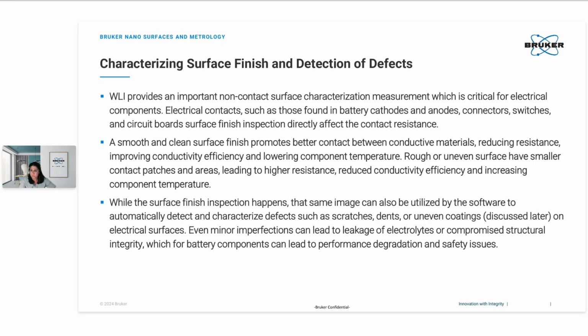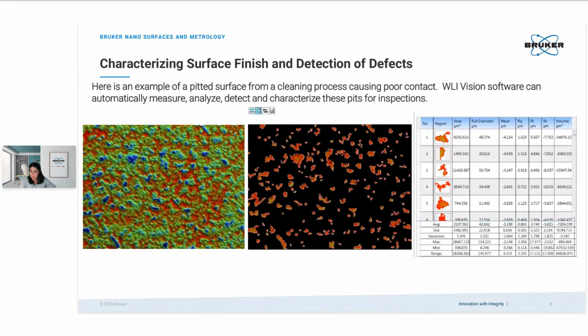And when we take a look at some examples, this is a very great example where you can see a highly pitted surface, which is pitted from a cleaning process. This pitted surface can cause poor contact. When we are measuring now with WLI, we can fully automatically measure the surface itself, but then also analyze and detect the pits and get a full overview of the quality of the surface.